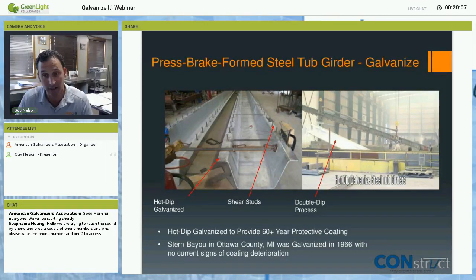If you see on the right, that is our 80-foot long press brake tub girder being progressively dipped to get a coating along the whole length, a continuous coating along the whole length. We did have to weld splice that to get it 80 feet long. We spliced a 50-foot and a 30-foot piece together. The galvanized coating provides a 60-year plus coating life, and that's just the coating life.